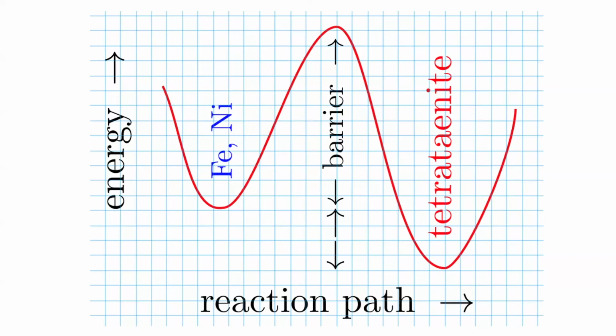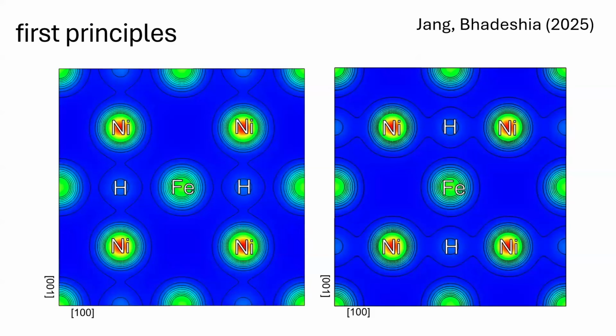So in the meantime, we did first principles calculations to show that if we can introduce hydrogen, and anything you add to this must be at a low temperature, right? Because it disorders about 300. And hydrogen is a small atom which can diffuse very rapidly. All right, so you might ask, well, how can we hold hydrogen in a cylinder? Well, it's molecular hydrogen, it's not atomic hydrogen. So if we can add hydrogen to this, then we would have an even better permanent magnet. So, we have to do something in the meantime, and we did these calculations to show that.